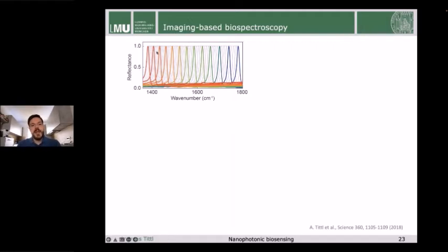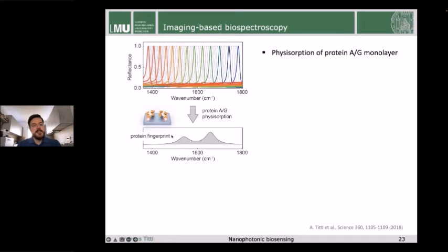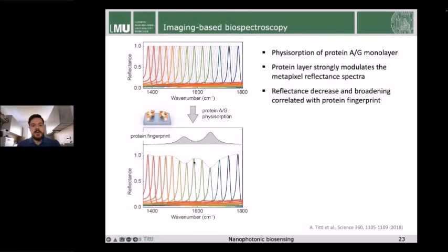So first you record the reflectance spectra of all these pixels. Then you apply some target molecule. In our case, we physisorbed a protein A/G monolayer. And then you look at how the spectra of the individual metapixels change. And you see that in spectral regions where the resonance overlaps with a protein absorption band, with the vibrational band, you can see a decrease and broadening of these metapixel resonances. Whereas in areas where there's no absorption, the signal stays mostly unchanged. So if I bring in again all the spectra, you see that the envelope of the spectra very nicely reproduces the protein fingerprint that we want to detect.